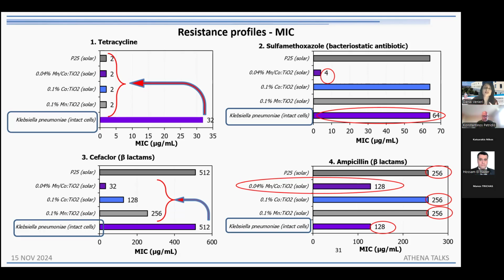So, for example, regarding tetracycline, in intact cells, 32 microgram per ml of tetracycline were required to inactivate that bacterium. And after treatment, only 2, which means that that antibiotic-resistant bacterial species altered its profile after treatment. Since the bacterium required only 2 microgram per ml, it means that it became more sensitive. So this is another benefit, but of course this is not the main result that we could get from every single bacterium or for every single antibiotic.